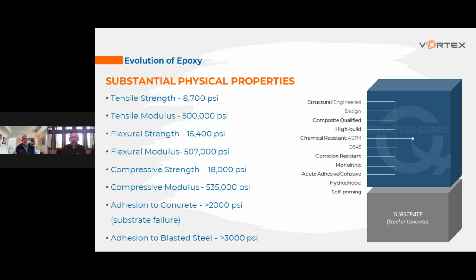Right. What is the typical curing time for epoxy coatings for manholes or inflow channels? Yeah, so within 4 hours, this material, the Structure Guard, after application is going to be substantially cured to where you can return to service.